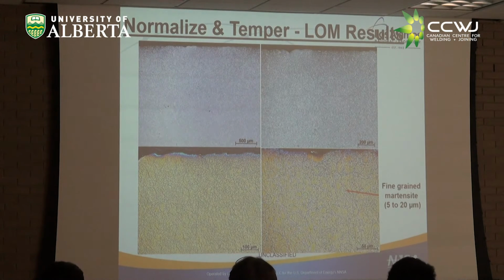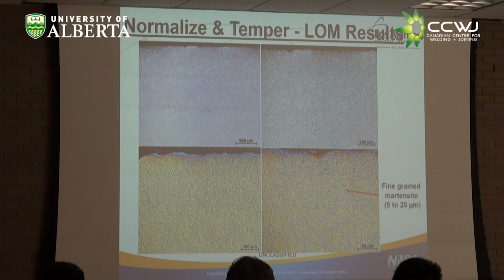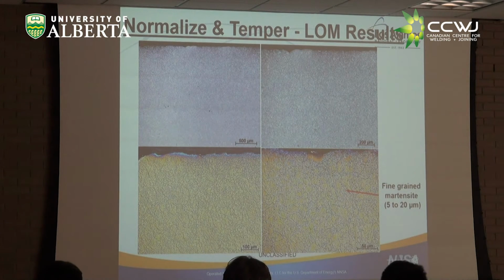I won't show you the direct tempered. As deposited, you went back and direct tempered it. Well, you temper martensite. If you don't have martensite, you're not tempering the martensite, and all you do is form bunches of carbides, which is not really exciting. So I'm going to skip that altogether. The as deposited, very confusing.